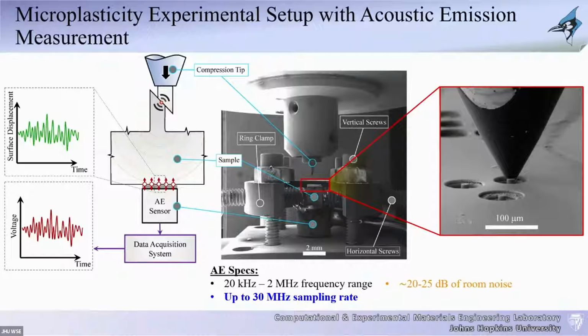Because with acoustics, the neat thing is the acquisition rate, the response that you get from those sensors that you put on the surface, is on the order of 30 megahertz. With the loading stages that we have, when we simply look at the load displacement, the acquisition rate is typically on the order of a kilohertz. So it's a significant amount of information that you can extract out of these types of acoustic emission measurements.